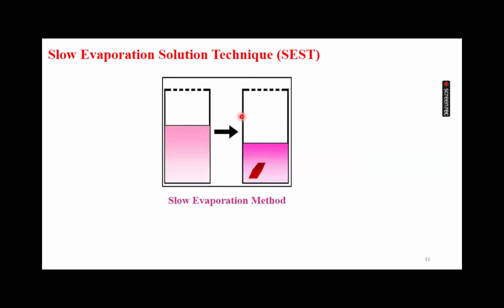Slow evaporation technique. Here, the most popular solvent is water. The saturated solution is created by combining the right solvent with the initial components and dissolving them. Through gradual evaporation at consistent temperature, it reaches the supersaturation point. A perforated lid is placed on top of the finely prepared saturated solution before it is transferred to a dust-free clean container. This technique includes stabilizing the temperature to around 0.005 degrees Celsius and evaporating at rates of a few cc per hour.